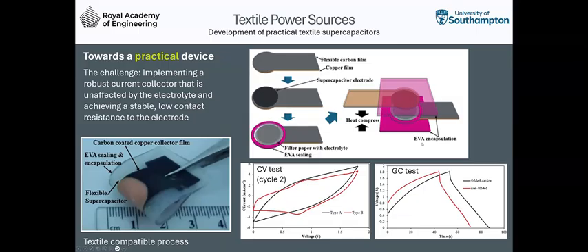So I mentioned about the encapsulation. So the challenge really with this technology is how do you transfer this device onto a textile, onto a garment in a reliable way. So we have to use an electrolyte that's like a solid electrolyte. So, aqueous electrolytes are not very practical. And we have to combine that with the current collectors. The challenge we have is that typically the current collectors react with the electrolyte during the charge transfer process. And the current collectors very quickly deteriorate and affect the performance of the device.